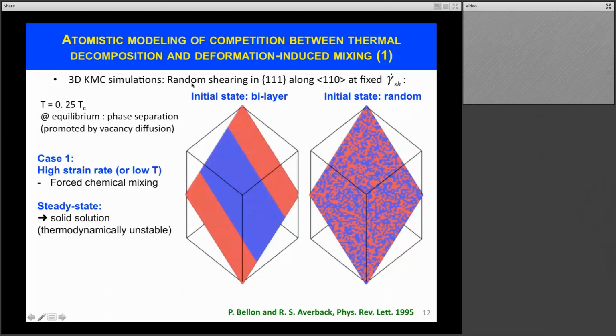From now here, this shearing is going to be taking place randomly in any of the four 111 planes of the FCC structure, along any of the three or six 110 directions in one given 111 plane. The only thing we're going to set or impose is the shear strain rate, or the shear rate here.